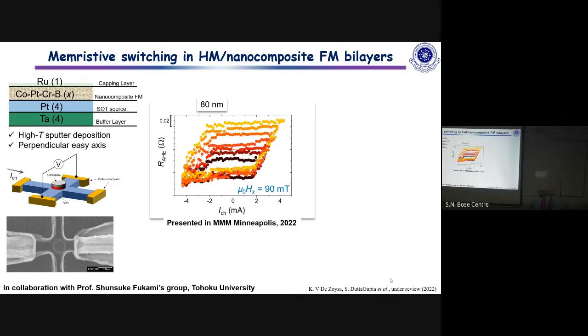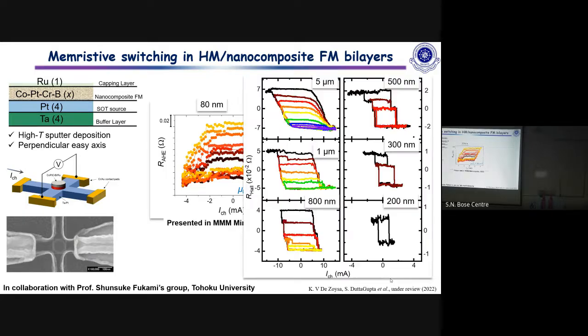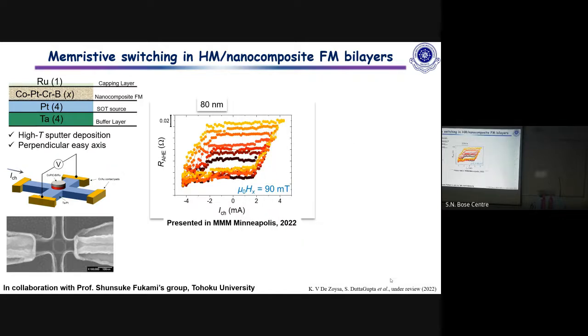This is a device of around 50 nanometer diameter, as you can see here. With these devices, we can get multi-level behavior down to 80 nanometers, which, from the spintronics approach, is probably the smallest device where you can get this multi-level behavior. This is our previous data, the work we did using platinum manganese, where the multi-level behavior vanished at 200 nanometers. But now we can clearly have this behavior at a diameter of 80 nanometers. So you can claim that we have been more or less successful in showing the world's smallest spintronic memristor at this point.